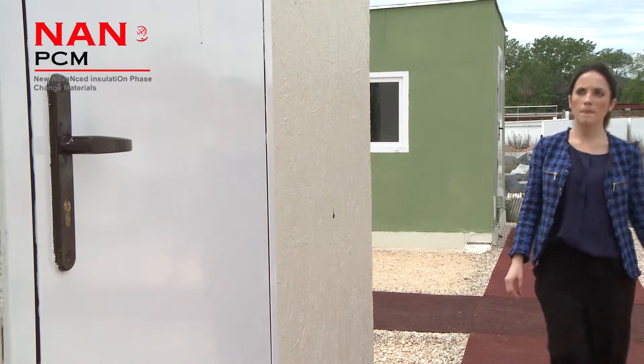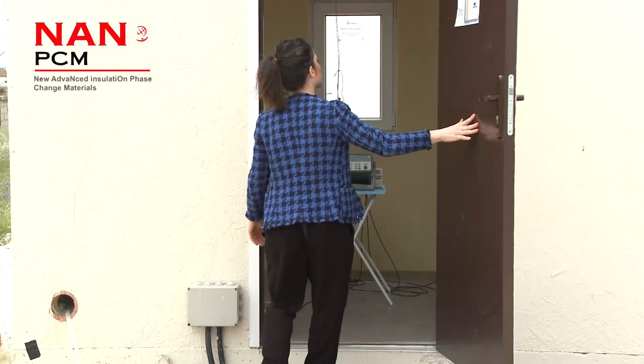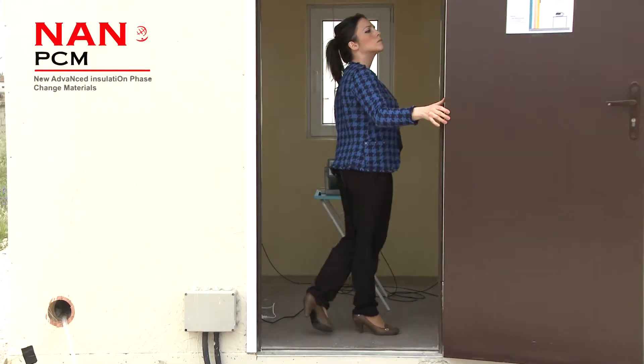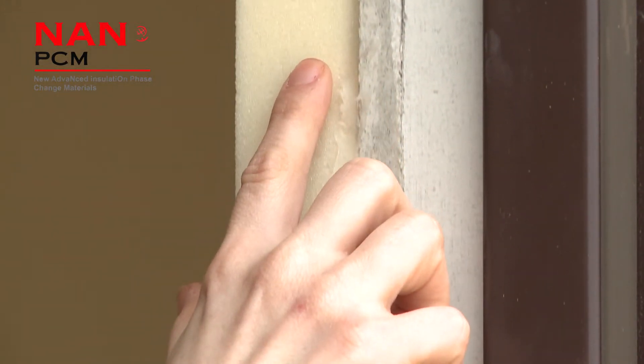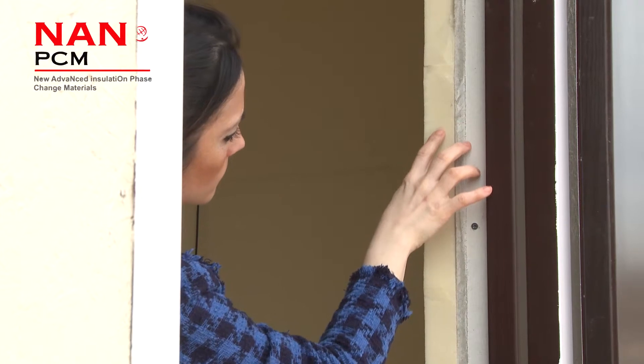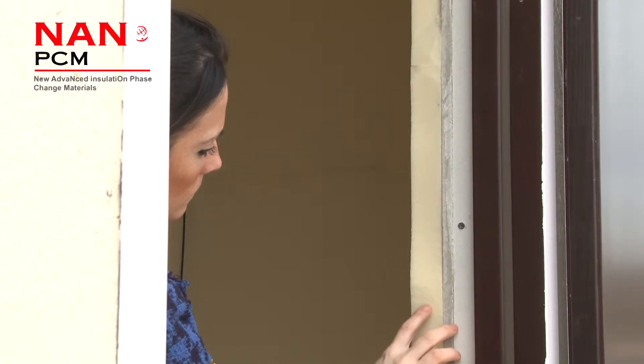We have developed different kinds of energy storage insulation foam, using nanotechnology to improve the thermal properties. We constructed several prototypes made of one or more layers. Lab tests showed that the innovative product can store five times the heat accumulated by traditional foam and can reach nine degrees lower than the typical one.